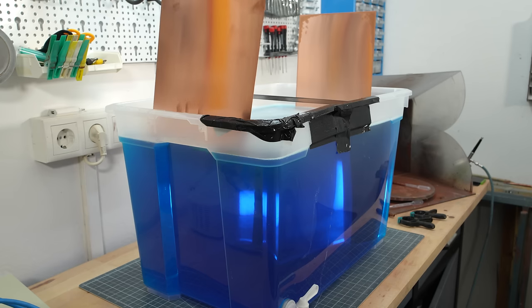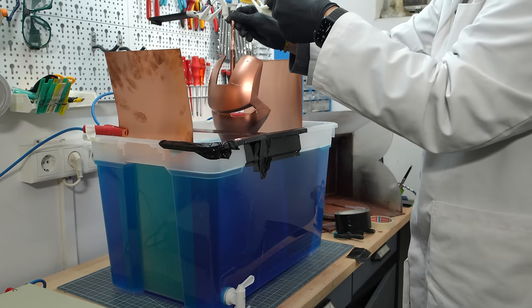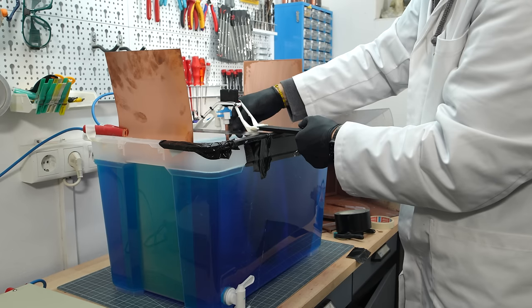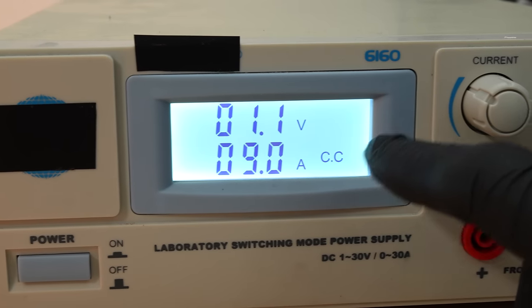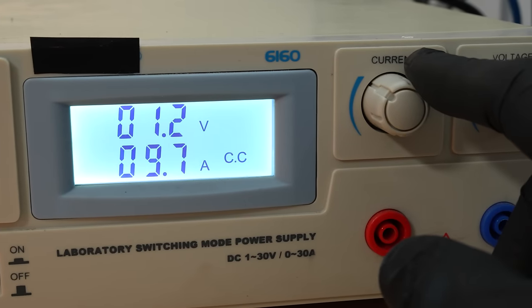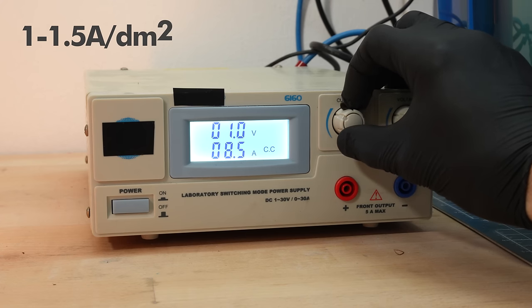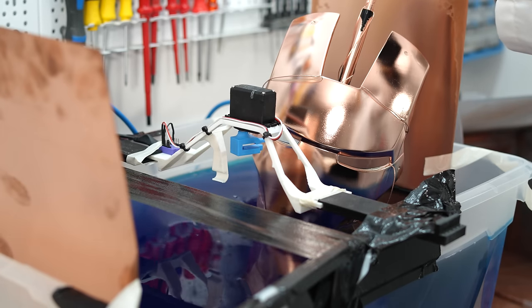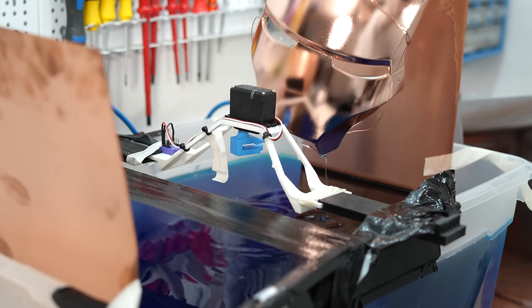Copper anodes are placed inside, then the 3D print is hung on the jig and the power supply is set to the correct constant current. This is crucial. I use 1 to 1.5 amps per square decimeter of the surface to be plated. After about 4 hours, we have achieved a layer thickness of 170 micrometers.